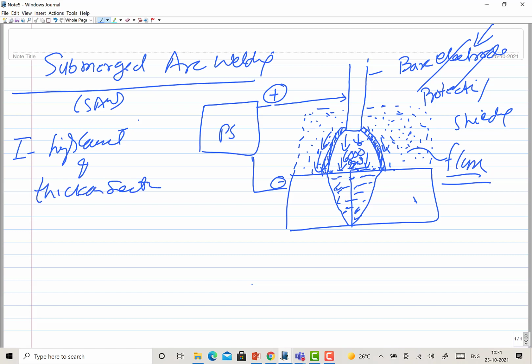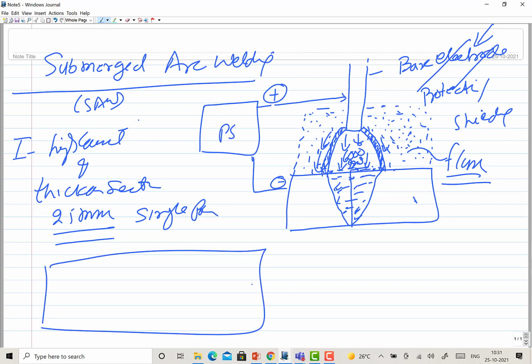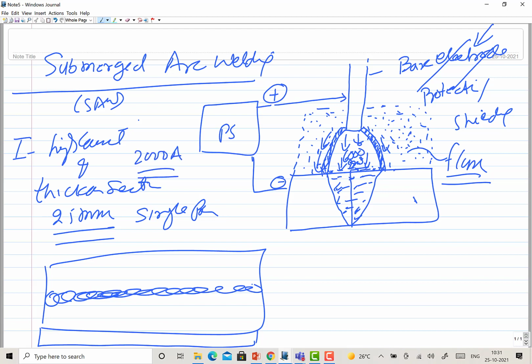So up to 25 mm thick plate you can weld in a single pass. So there is a sheet of say 25 or 40, just pass the arc once, so through thickness penetration will be realized in one go because of the high current feature associated with the SAW process. Current as high as 2000 ampere can be supplied to the electrode depending upon the diameter again. Starting from 300 to 2000 ampere current is very commonly used in SAW, submerged arc welding process.